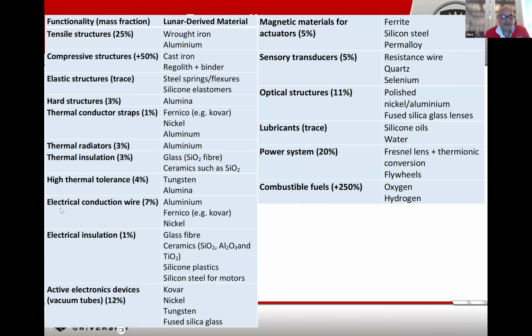So for example, electrically conducting wire, that's about 7% roughly of a spacecraft's mass. We can use aluminium, we can use Fernico, such as Kovar, for high temperatures, and we could also potentially use nickel. If we look at electrical insulation, we can use things like glass fiber, we can use ceramics of various kinds, we potentially can use silicone plastics, but I've pretty much discarded that more recently. The advantage of silicone plastics is that the backbone is not made of carbon, it's only the side chains which are carbon, so that minimizes the amount of carbon consumption.